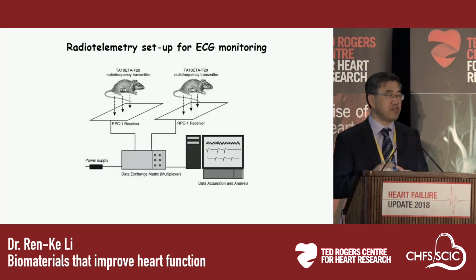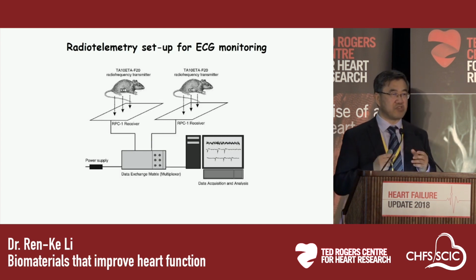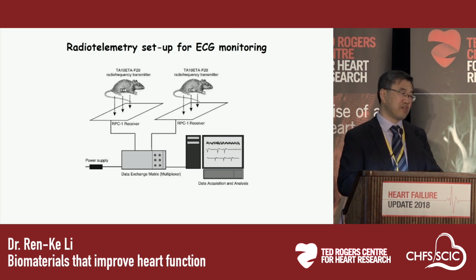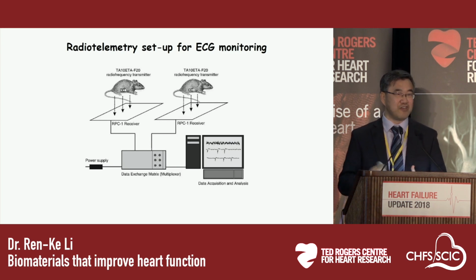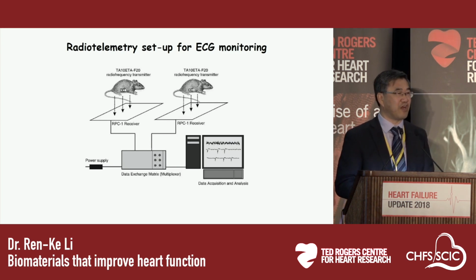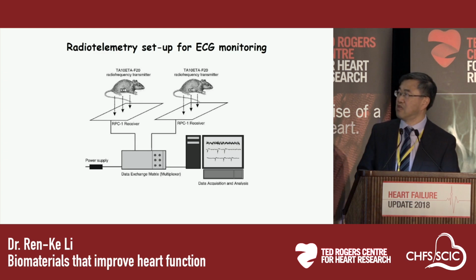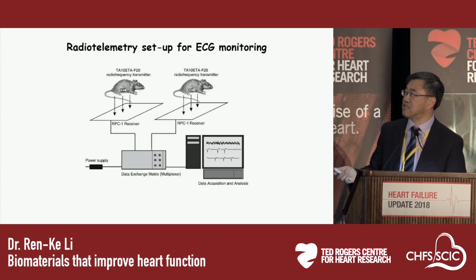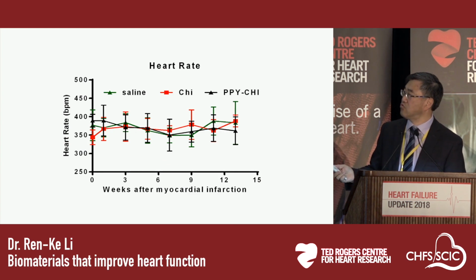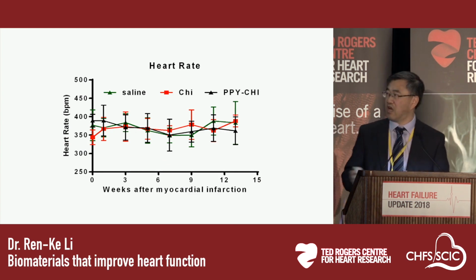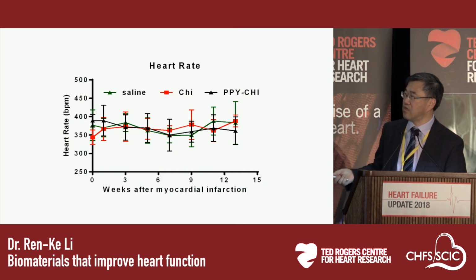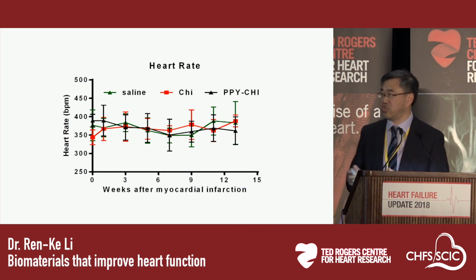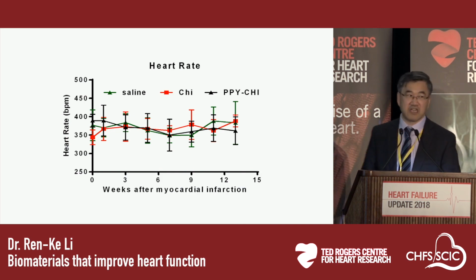When we tried to inject the conductive biomaterial to reduce arrhythmia, people said if you put it over there, you may initiate arrhythmia because you put the conductive biomaterial into the heart. That might be the problem. So what we did is we did telemetry in the rat, with 72 hours recording, and this is the heart rate monitor. We found the heart rate did not change after we injected the conductive biomaterial.